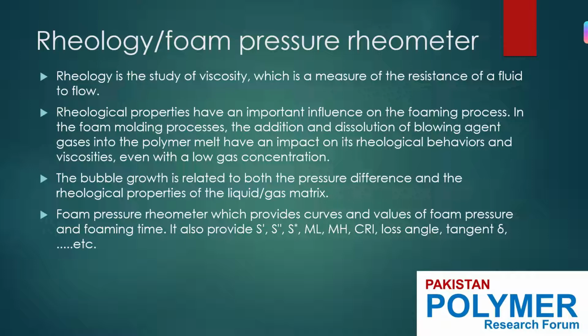Because the nucleation density is mostly determined by the pressure drop rate in a mold compared to the solubility pressure of supersaturated polymers. If I talk about the bubble growth, it is related to both the pressure difference and the rheological properties of the liquid gas matrix. There are different mathematical models available to understand the bubble growth in terms of rheology. I can name a few, which include the power law or the Maxwell melt laws and the mass and momentum transfer. People have contributed in this field by calculating different equations, but I'll not go into such details. I'm sharing just the general perspective of rheology.